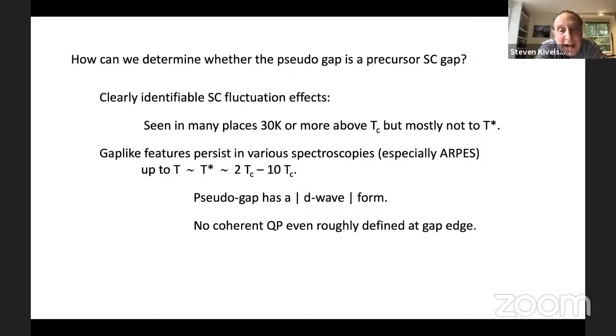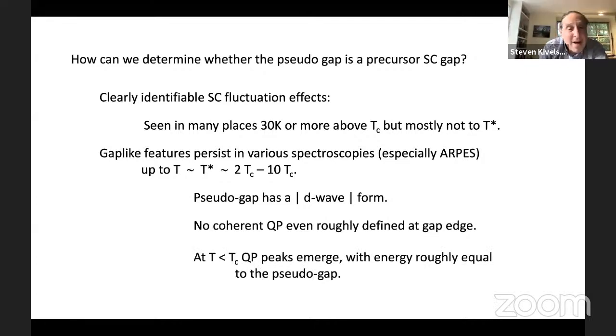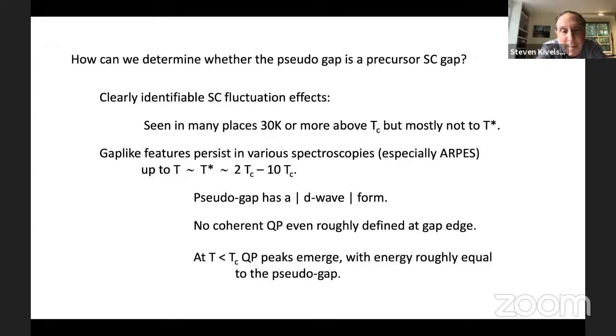However, it's not even really clear what you mean by this gap. In ARPES at least, there are no coherent quasi-particle peaks — it's some recession of spectral weight from the Fermi energy rather than the position of a well-defined quasi-particle. On the other hand, as one cools below TC, a quasi-particle peak does appear with an energy roughly equal to the pseudogap energy, which evolves into a nice D-wave quasi-particle at temperatures well below TC. So there's an argument from continuity that perhaps the pseudogap and the superconducting gap below TC are linked.